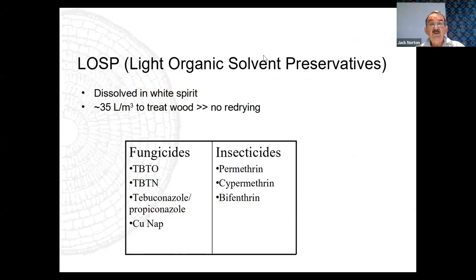Organic solvent preservatives, you will see this sometimes on things like balustrading, handrail. As I said before, they're dissolved in organic solvents. The beauty of these things is that you treat them in final shape and form. When you treat with a water-based preservative, it raises the grain. Pine will absorb about 500 to 600 litres a cubic metre of water. Hardwoods will probably absorb somewhere in the order of 300 to 400 litres per cubic metre. So when you start absorbing those quantities of water, the wood will swell and it will raise the grain. With LOSP preservatives, that doesn't happen. And there the fungicides kill the fungi and there the insecticides.